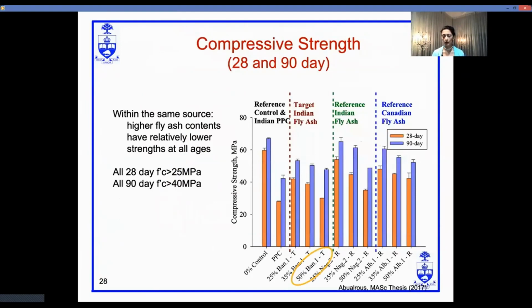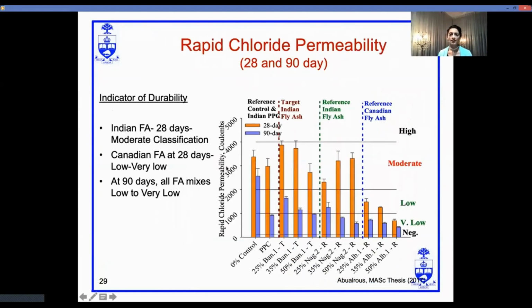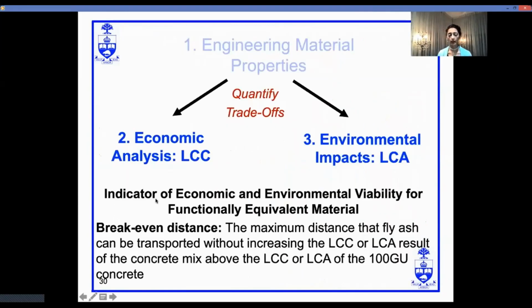Beyond the actual material characterization itself, we, of course, looked at the concrete properties and performance, and what we found was that the performance was very good at both 28 days and 90 days, for all of the mixtures with the different types of fly ash from the different communities. At 28 days, we had compressive strengths greater than 25 megapascals, and at 90 days, strengths greater than 40 MPa. Similarly, our rapid chloride permeability data was quite good. We had moderate RCPT at 28 days for the target communities, and all within the range, low or very low at 90 days. So that was considered to be quite good.